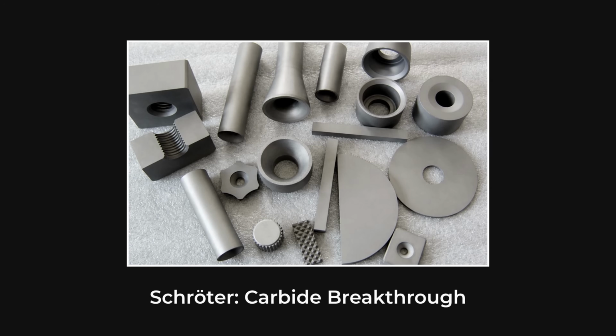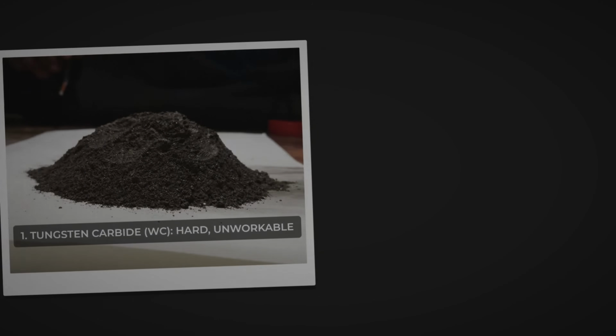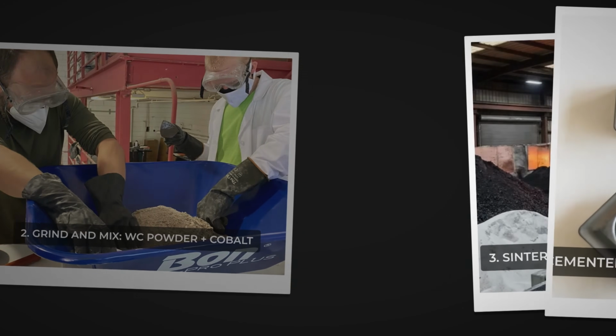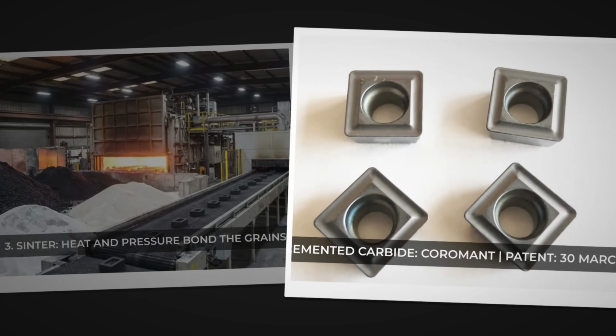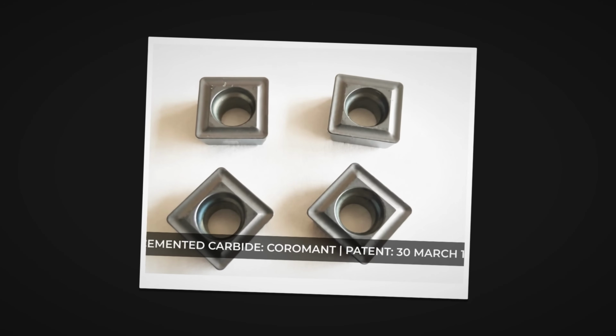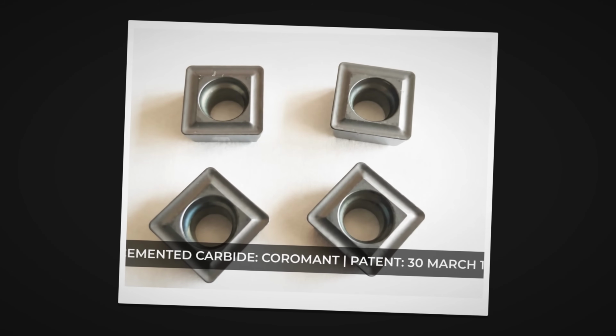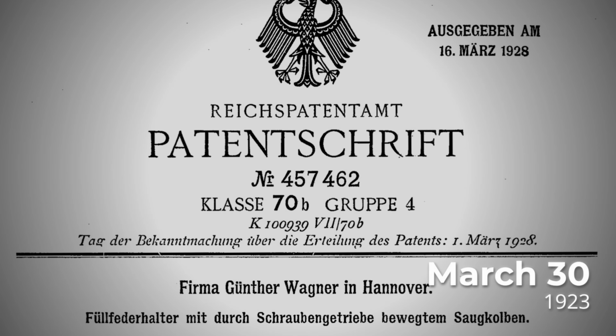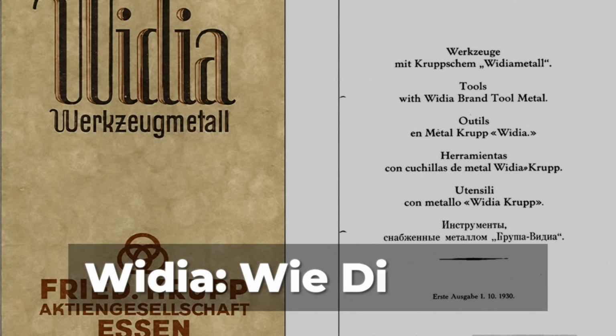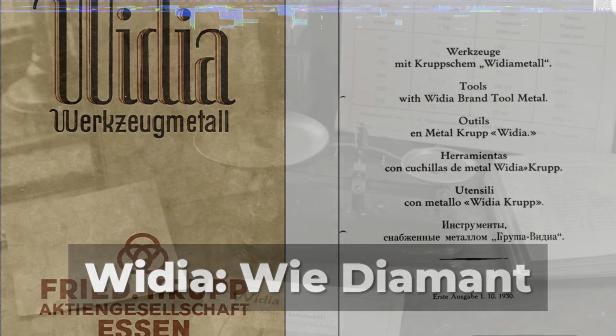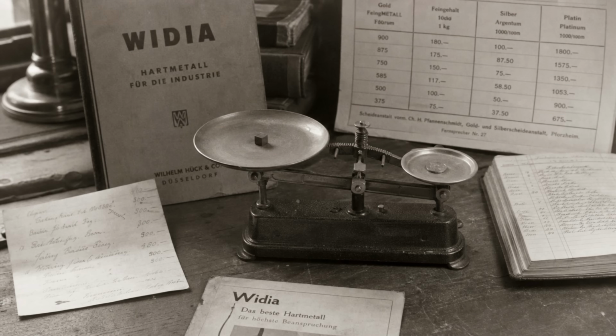Schröter's answer was to take tungsten carbide, which is fantastically hard and completely unworkable on its own. Grind it to powder, mix it with a small amount of cobalt, and heat the mixture until the cobalt melted and glued the carbide grains into a solid mass. The patent was filed on the 30th of March, 1923. Krupp licensed it and put it on the market as Widia, short for Wie Diamant, German for like diamond. In its first years, 1 gram of the stuff cost more than 1 gram of gold.